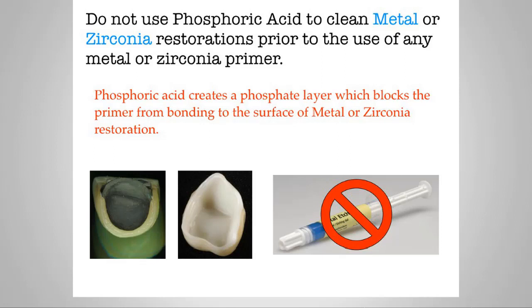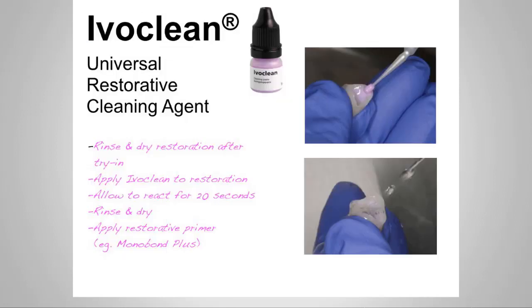For other materials other than metal and zirconia, we can use phosphoric acid to do that. With zirconia and/or PFM, if you're trying to bond to that, you cannot use phosphoric acid to clean that surface. You're going to need to use something that is more like a universal cleanser, like the Ivoclean. My recommendation is use Ivoclean on every crown to clean it before you cement it. That's going to be a safe thing to do, and more than likely you're going to really increase your bond to that intaglio surface. It's really easy to use. You paint it on, let it react for 20 seconds, and then you rinse it off.